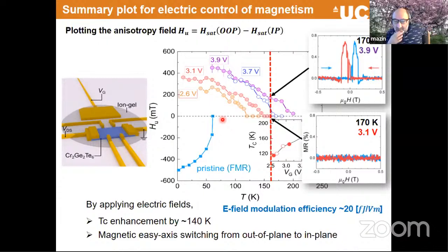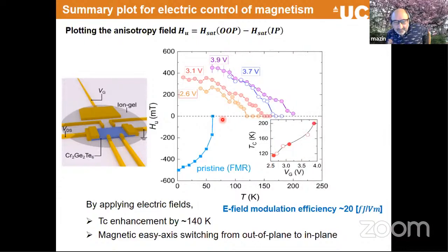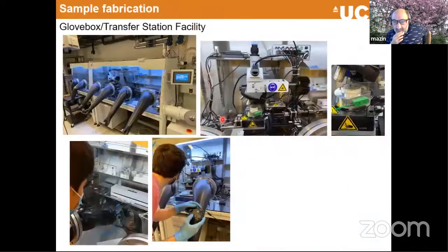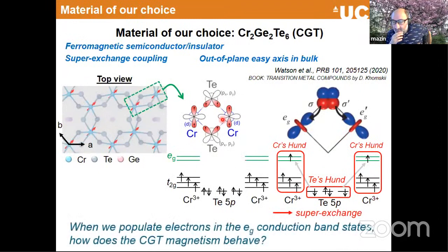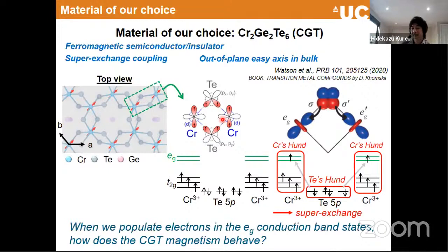So it's a little bit in line with the previous question. If you go back to your Hubbard model diagram, it's quite clear from that that any doping can only reduce the tendency to ferromagnetism, because it's very simple. If you just fill your EG band completely, you get manganese 2+, a very strong antiferromagnet. So, as Daniel alluded to, the only possible way this doping can make it more ferromagnetic is because of metallization, because of a metallic effect, sometimes a sort of double exchange, and then it would be very strongly correlated with metallic conductivity and so on.